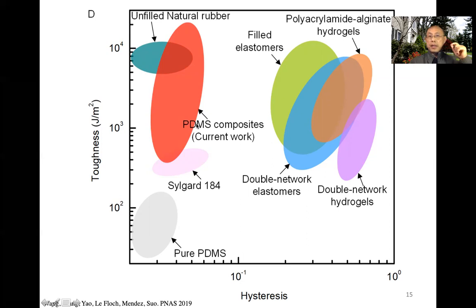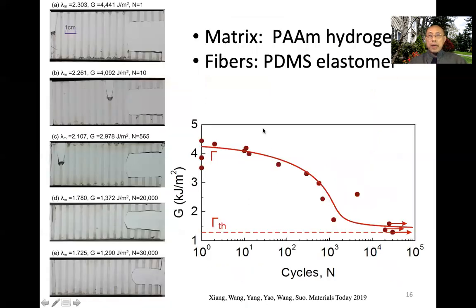Now, if you just test homogeneous PDMS, this is Sylgard we're using, the toughness is very low, about several hundred joules per meter squared. It doesn't matter if you make it soft or hard, as long as it is homogeneous, the toughness of PDMS is low. People have experience: PDMS is much more brittle than natural rubber. That's common experience. All right, and then we also made a version of a composite. For the matrix we use hydrogel, and for the fiber we use PDMS.